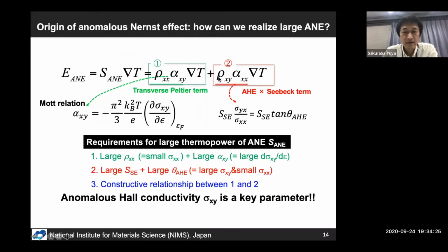Yeah, so I can say that the second term is very simple. When we apply a temperature gradient, the Seebeck effect causes carrier transfer, and the anomalous Hall effect gives a transverse electric field from the Seebeck effect. And this alpha XY can be considered as a kind of direct conversion from the temperature gradient to the transverse electric field.